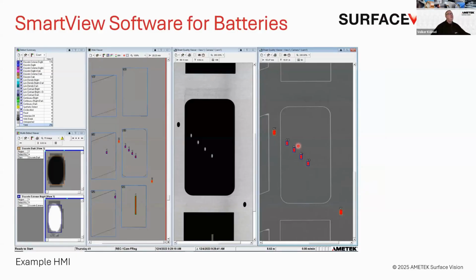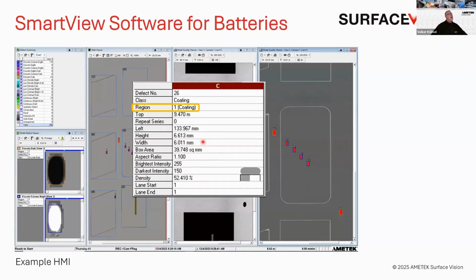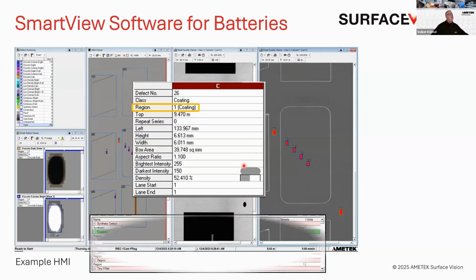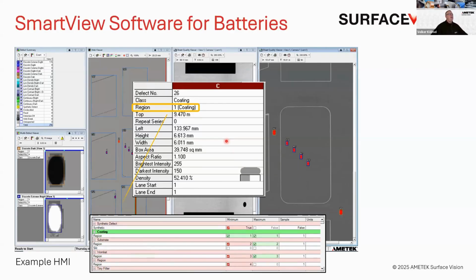This is, for example, a user interface, how this could look like, where we identify on those blue sheets the coated area, and you see a little bit of shape, so you understand what is behind. And when we find defects, we will also tell you if the defect was found on the coated area or on the substrate area. And this information can also be used later in the classification. Say, well, I would like to have a unique feature when it is on coating or off coating. So this is when we talk about defect detection.